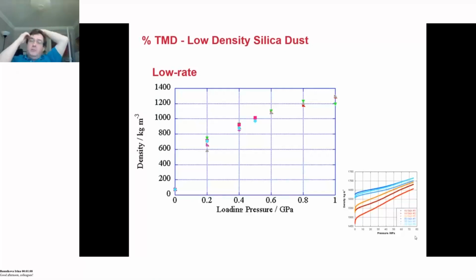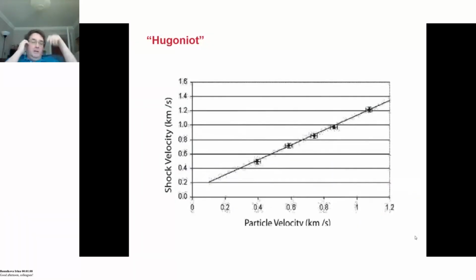If you try and work out a Hugoniot from this, and this is one of my favorite curves because it shows me not really thinking too clearly at the time as I did this analysis. Shock velocity versus particle velocity. So here is the shock velocity predicted from my gauges. Seems like a quite nice straight line.